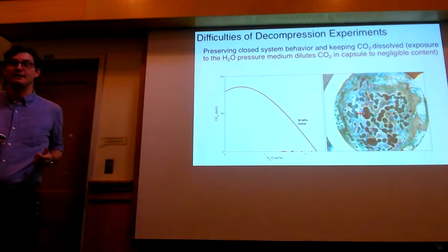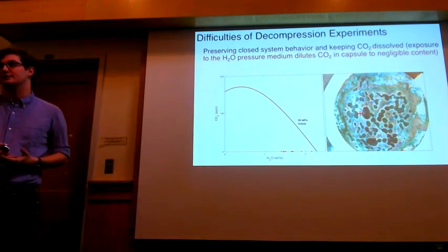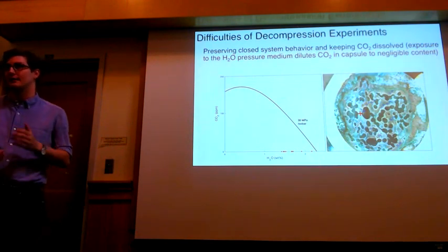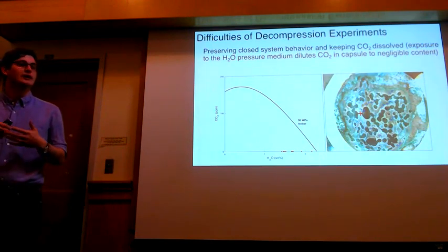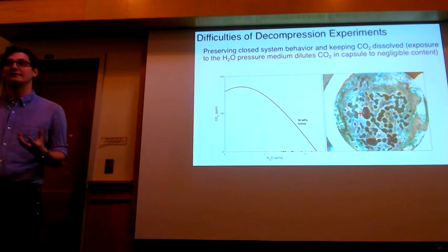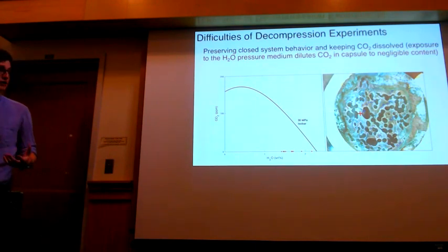We changed some things to combat that. First, we started annealing our capsules at 1,000 degrees Celsius, which had the goal of healing microfractures and then trying to correct some of the manufacturing defects. And then we also started using thick-walled gold capsules, but that comes at greater expense and inconvenience because we had to have them custom made. But that started to work out pretty well.